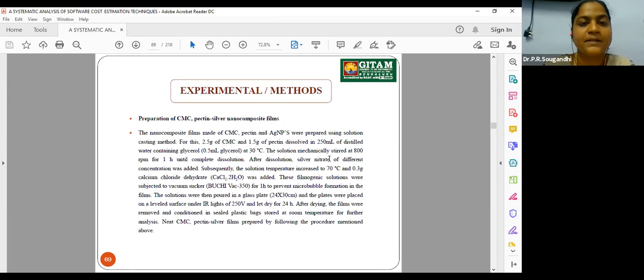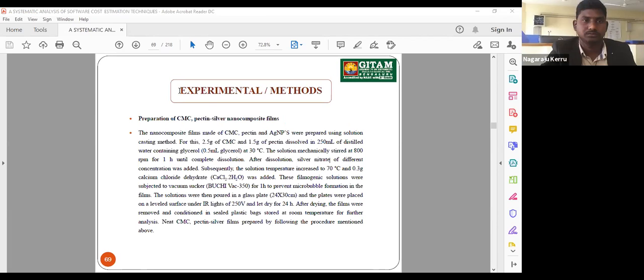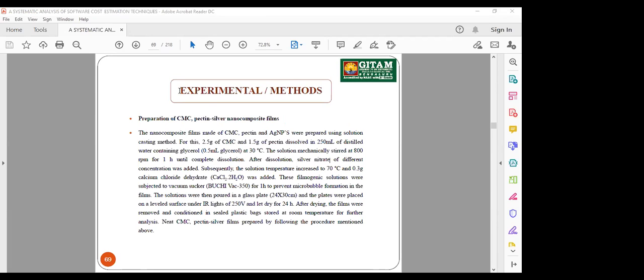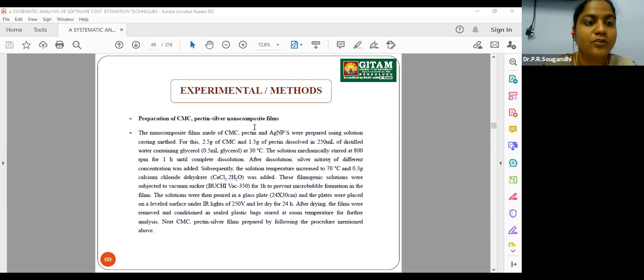So coming to the experimental method, the preparation of film. How do we prepare the film? The film is prepared by using a technique called the solution casting method. In this, the two polymers, CMC and pectin, were dissolved in distilled water, and then glycerol is added to this.